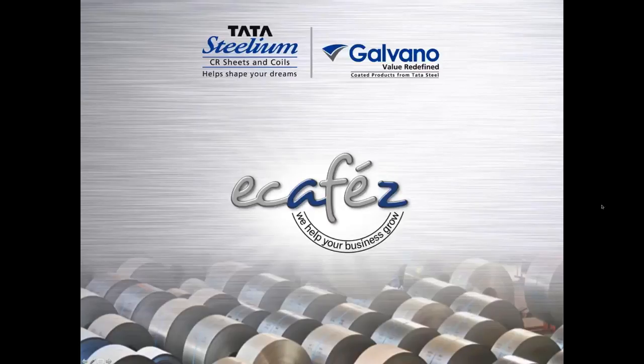Mr. Saurabh Srivastav is asking what process to follow in the dual powder coating process. I think a lot of people are interested in powder coating. Dual powder coating is usually the first coat like a zinc rich primer, only it is in powder form. If you look at their specifications, they'll ask you to bake it at a little lower temperature, usually 160 to 170 degrees, so that the epoxy is not fully cured. Then you apply the second coat and again it goes for baking. That time the first primer coat is baked. So usually that is how we use it.